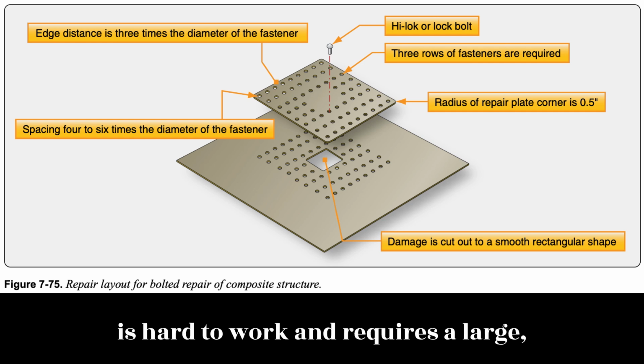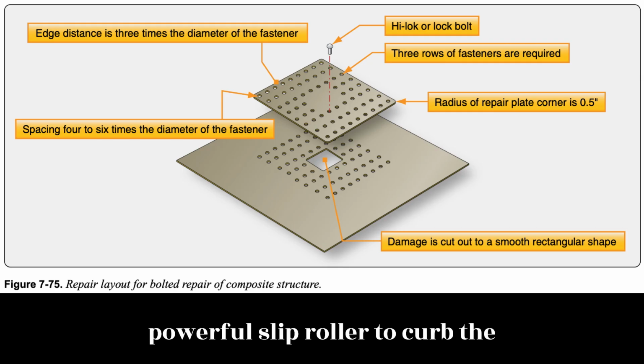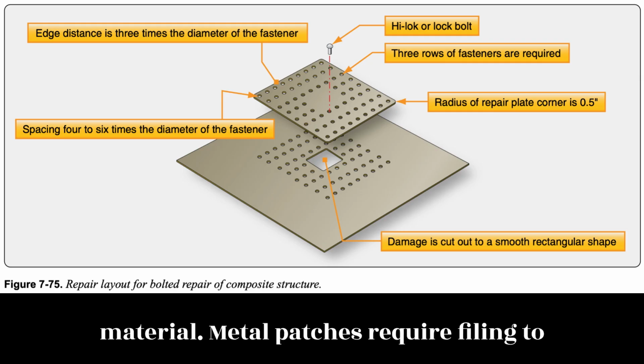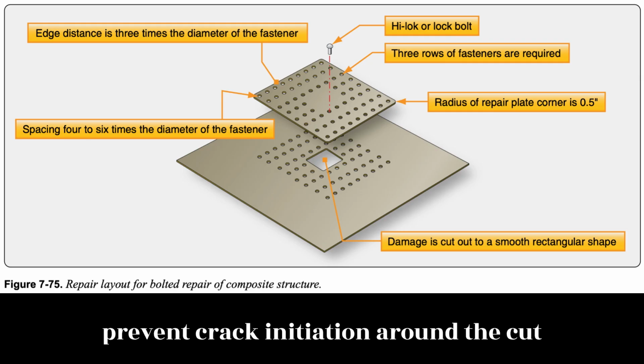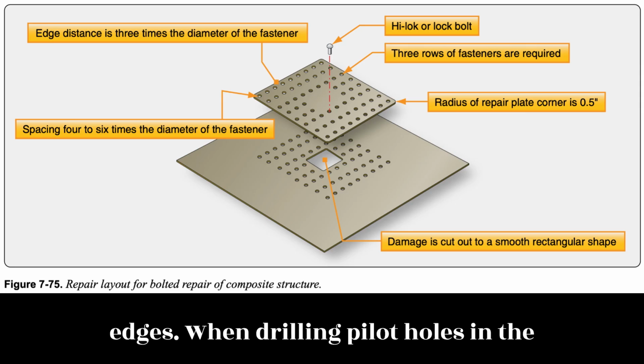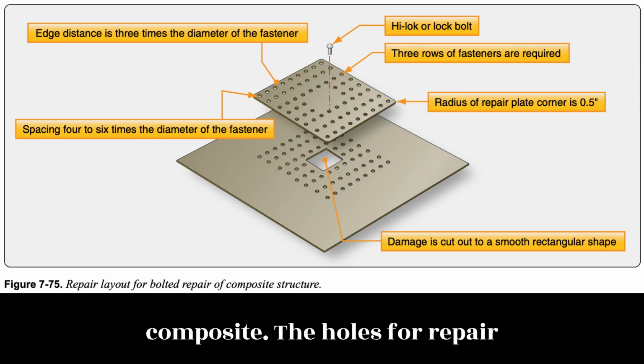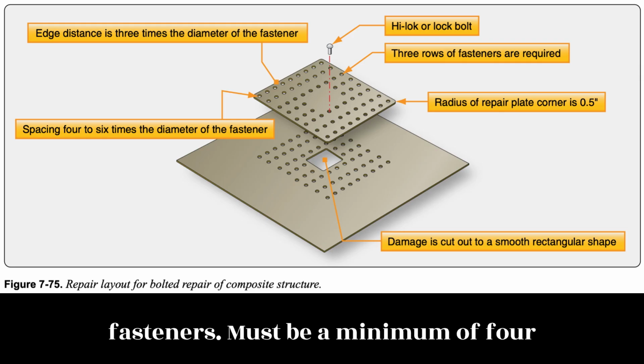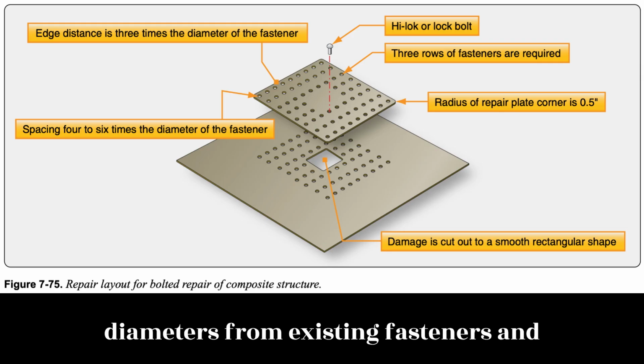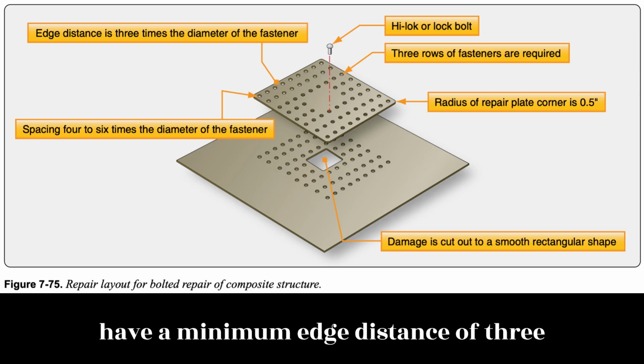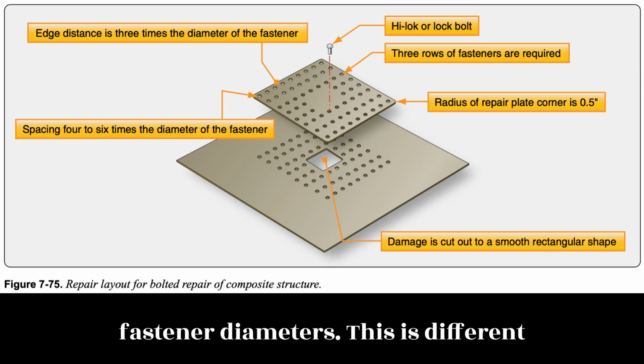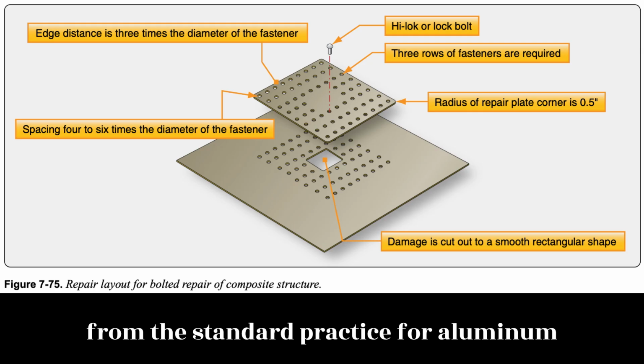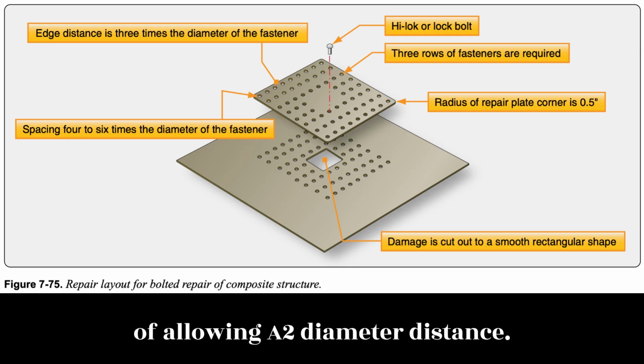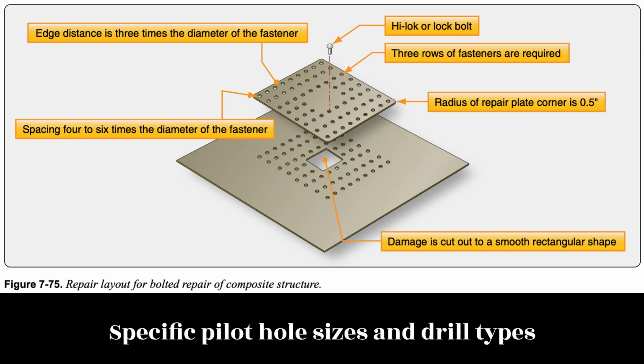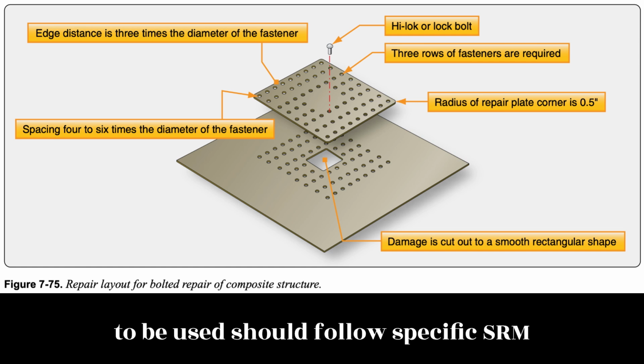Titanium is hard to work and requires a large, powerful slip roller to curve the material. Metal patches require filing to prevent crack initiation around the cut edges. When drilling pilot holes in the composite, the holes for repair fasteners must be a minimum of 4 diameters from existing fasteners and have a minimum edge distance of 3 fastener diameters. This is different from the standard practice for aluminum of allowing a 2 diameter distance. Specific pilot hole sizes and drill types to be used should follow specific SRM instructions.